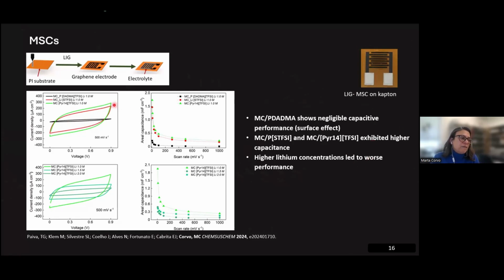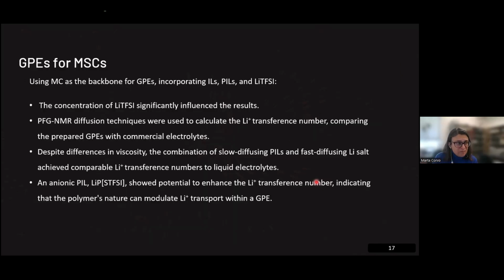But we find it quite promising to look at these other two, either the polyionic liquid or the ionic liquid version. Here we also saw that higher concentrations of lithium didn't give higher performances. That is in agreement with what we have seen earlier with the transference numbers. Here you can check the performance in the micro supercapacitor. For these devices, we saw that using methyl cellulose as a backbone could function quite well for gel polymer electrolytes with ionic liquids, polyionic liquids, and lithium bis(trifluoromethanesulfonyl)imide. The concentration of lithium, of course, influences the results, but it's not a linear progression in this work.